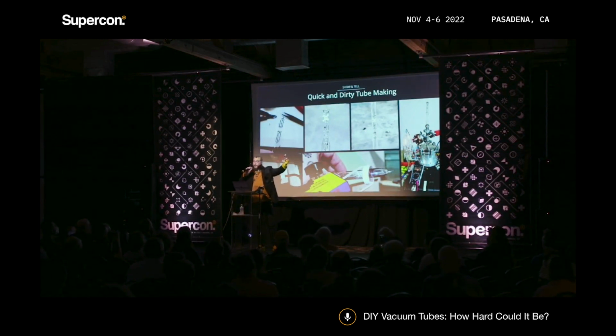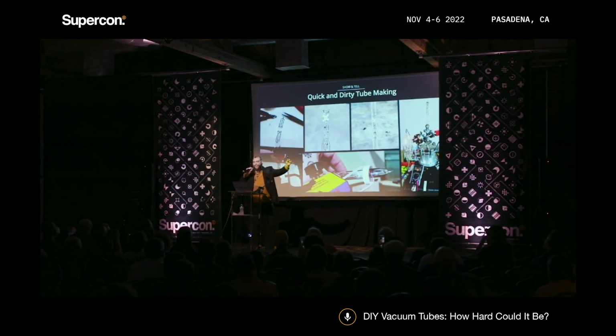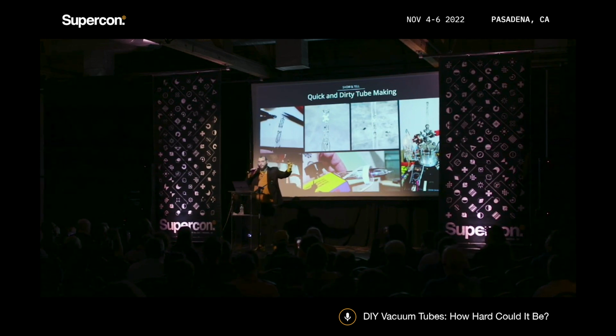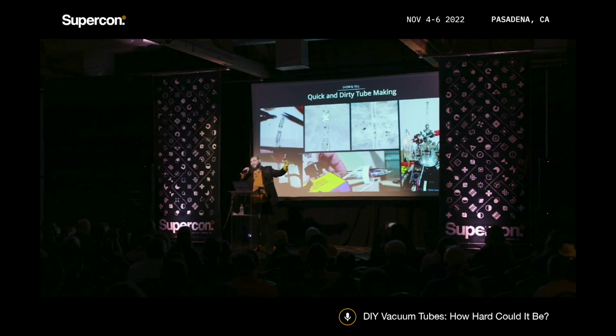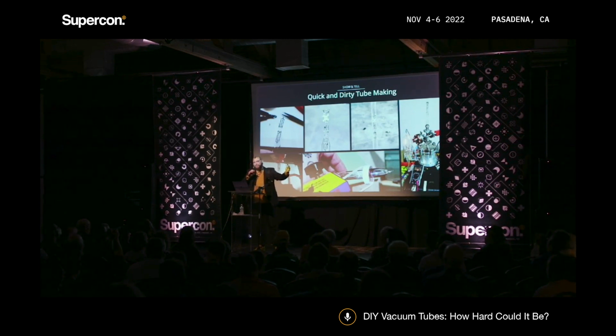It was supposed to be a homemade vacuum fluorescent display, but I mentioned earlier that the application process for the phosphor was opaque to me, and so I didn't know that till I powered it up. Apparently, I don't know how to do it. The silvery part on top is that barium getter. It's got a little Jolly Rancher anode in there. You can pass 120 milliwatts through it, at about 60 volts DC. So it's 2 milliamps at 60 volts DC. And the filament takes about 10 volts, a couple amps to heat up hot enough to actually get that thermionic emission. But it does indeed work.